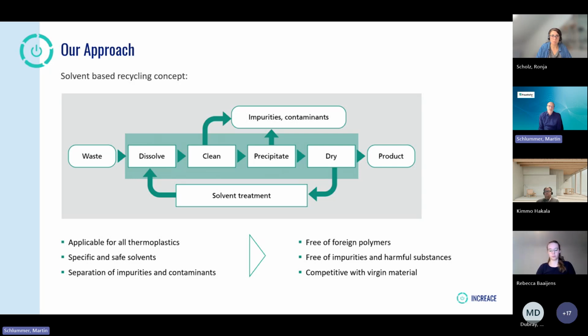And in the end, as the final product step is an extrusion, a degassing extrusion, we end up with a granulated product, which can directly be reused, or if you want to go back into some recompounding to adjust the product's properties. The basic idea is this is suitable for all thermoplastics. You can make this with very specific and also very safe solvents, and you can really highly purify impurities and contaminants. And in the end, you have, if you are lucky with your process, a material competitive with virgin feedstock.